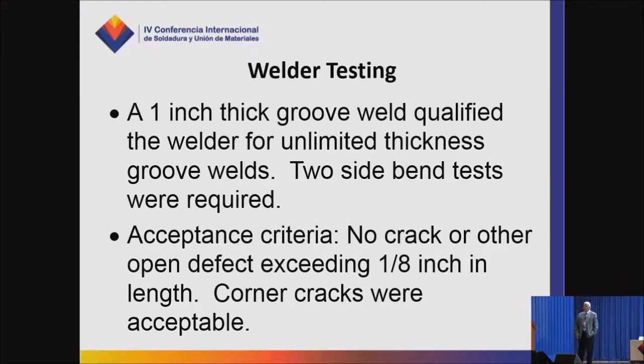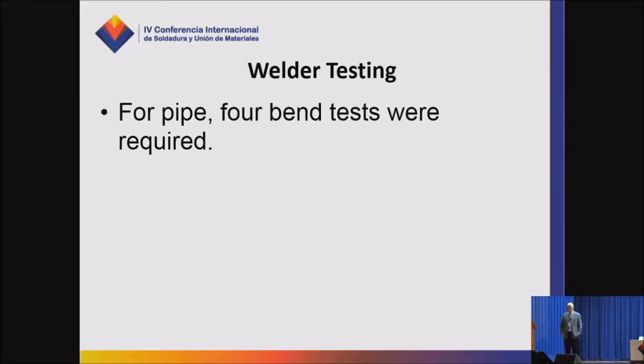You had to do 2 side bends if it was a plate test. Acceptance criteria. No crack or other open defect exceeding 1/8 inch in length. Corner cracks are acceptable. Same thing we have today. So, been in the code forever. If you tested the welder on pipe, because pipe positions were multi-positions, you had to do 4 tests.